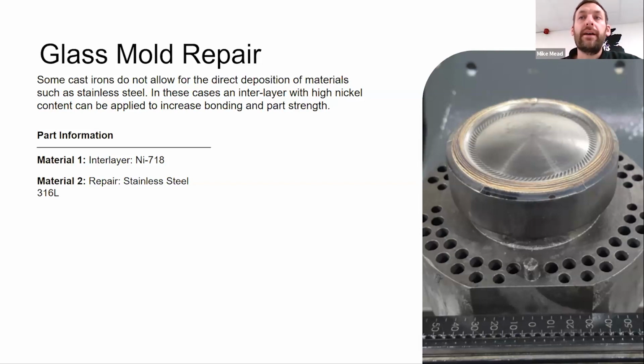So what we do is we create a layer in between, a sandwich layer or a butter layer, as you'll find it in welding terms. And we'll put that in with a nickel alloy. So in this instance, we've got nickel, we've got Inconel 718. And then once we've got that interface layer of the 718, we can go back and create our molding structure using the stainless steel 316L and then machine that back to shape again. So we're being able to use the different material properties to allow us to access areas of manufacturing that we wouldn't be able to access before.